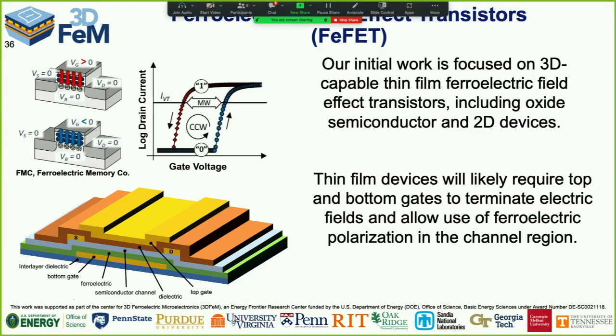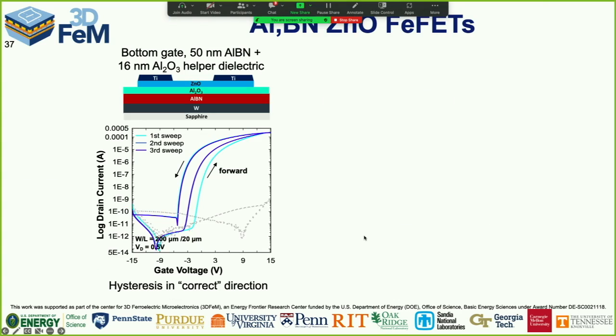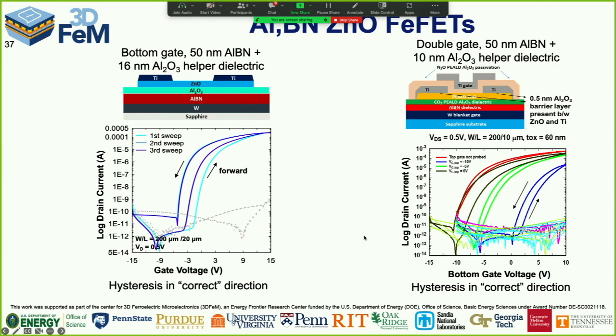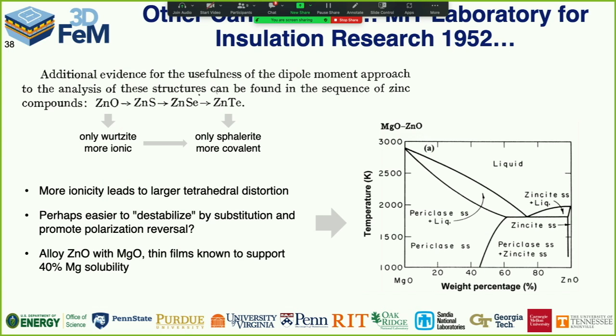And this is not a great material for a ferroelectric field effect transistor. Its polarization's too big, but let's try it anyway. And so my colleague Tom Jackson grew one in. He did end up using top and bottom gates so that he can terminate the electric field. And these are, honest to God, ferroelectric memory elements. So they show all of the transistor characteristics that one would hope for. But the coercive fields are still brutally high. Okay, 6 megavolts per centimeter. Now I got to get really, really thin before I hit a 1 volt switch.